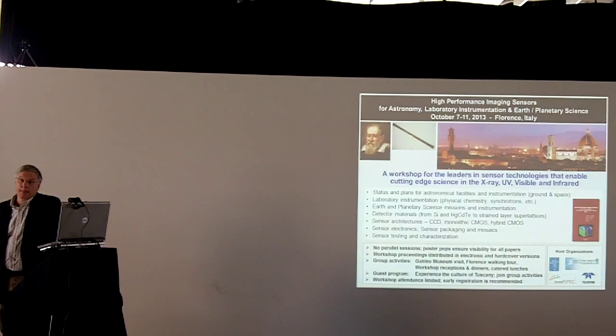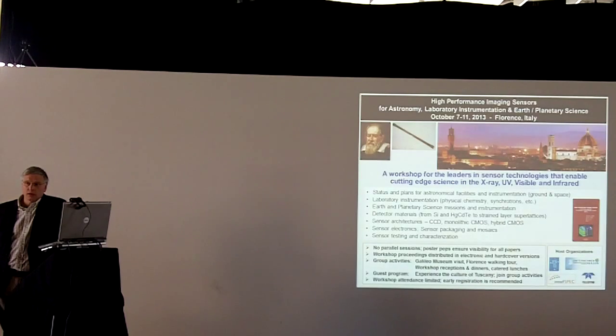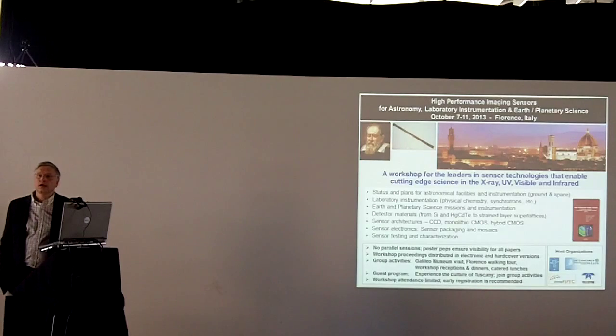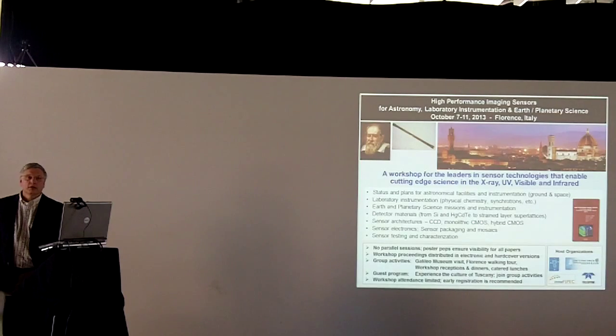I think we had another question here. Are you looking into any kind of epitaxial lift-off technology to be able to remove your substrates, like you do in solar cell manufacturing? So the question was, are we looking at epitaxial lift-off to try to remove the substrate? Yeah, so instead of polishing and then etching your substrates off, just putting in a release layer that you can chemically etch and heal your CCD or your detector. So the idea is to grow on a release layer and then pop that off. You'd have to have the right crystal lattice spacing and be a good crystal lattice.